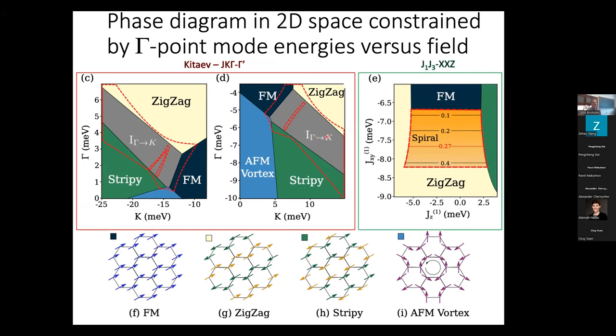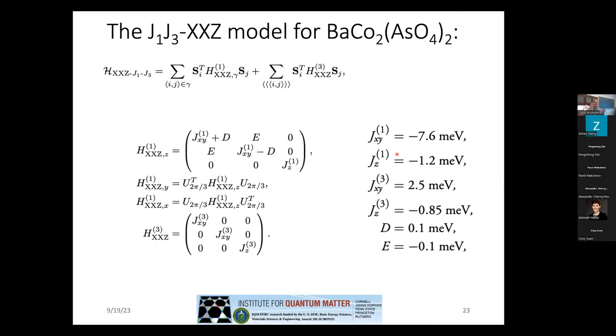So that actually is, we think, enough to exclude the straight out Kitaev model without a J3 interaction. Now, when you throw in the J3 interaction and turn to the XXZ model, then in fact, you do have a spiral state, which has a wave vector that is consistent with the experimentally determined low temperature component of in-plane wave vector. And you can now see to what extent that constrains the JZ interaction and the near neighbor Z component and easy plane type interaction. And so by combining these data, we first of all are able to exclude the Kitaev model, the near neighbor Kitaev model, as a description of the system.